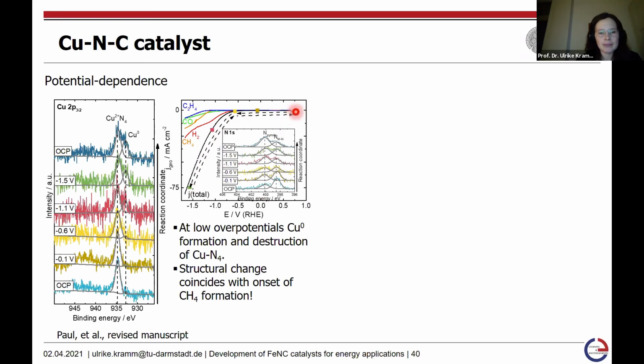Basically, how to explain? So let's say this red one was extracted at a potential of -1, but then we used a fresh electrode in order to prepare this green spectrum, which was then cycled, of course, up to this point. And there was a further point where basically it was first cycled in this direction and then cycled back to OCP in order to see the final state of the catalyst material. Here are the current density contributions to the different product formations on the Cu-N-C catalyst material.